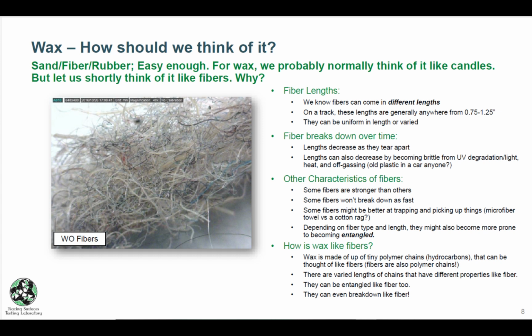You come through with a power harrow, for example, or just any harrow, that's going to break down the fibers over time. Well, we still see the same type of thing happening with wax. You leave the fiber out in the sun and it will become brittle through heat degradation, the UV degradation coming from the sun, off gassing. It's the same type of deal that's causing the plastic in older cars to become really brittle and break. We're talking about the same type of mechanisms here.